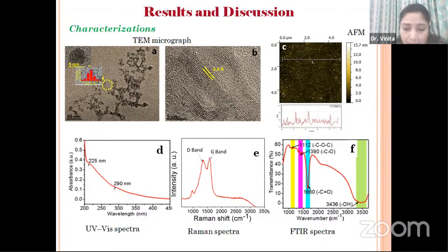Firstly, characterized by TEM images. Figures A and B show TEM images of the synthesized graphene quantum dots. The size ranges between 3 and 9 nanometers with an average size of 6 nanometers, confirming the formation of small size quantum dots. And figure B, the HRTEM, shows parallel lines of graphite with a spacing of almost 3.4 angstrom, indicating the crystallinity of the quantum dots. C shows the AFM images, with an average height of the GQD of almost 5 to 6 nanometers.